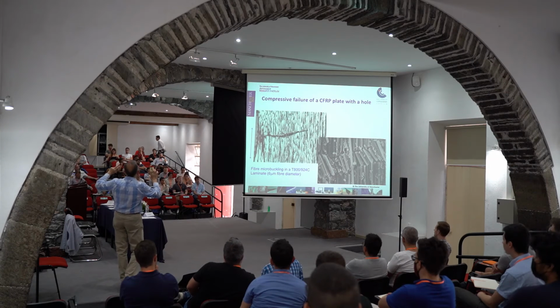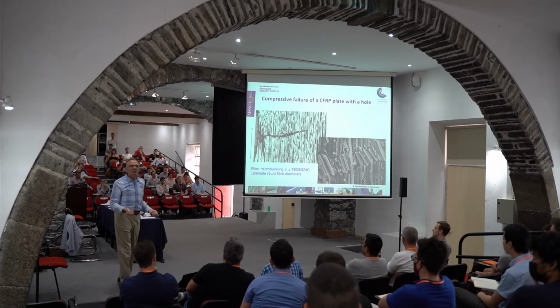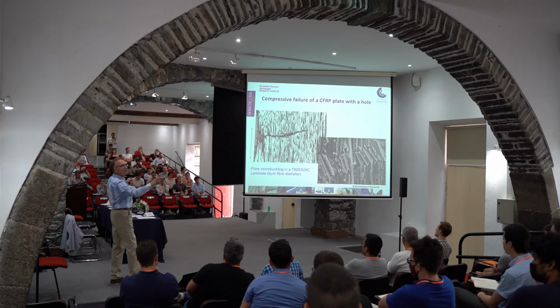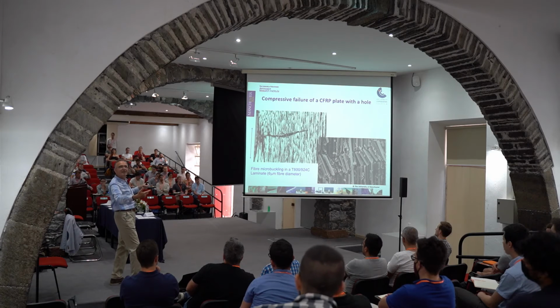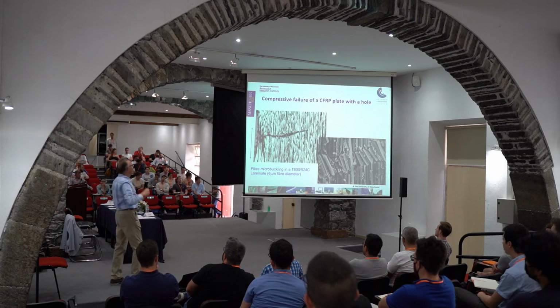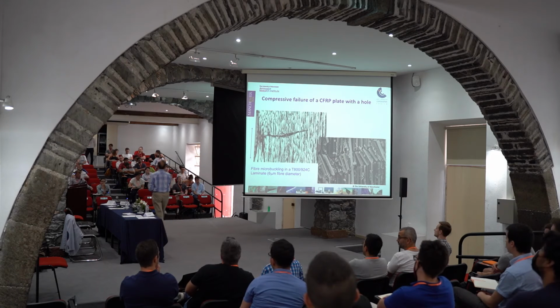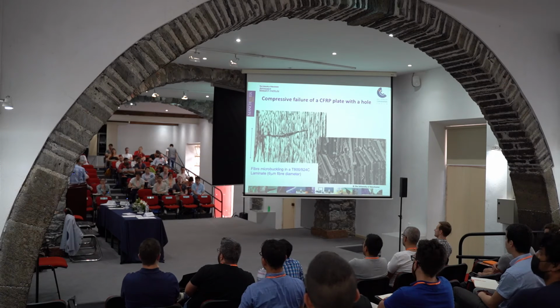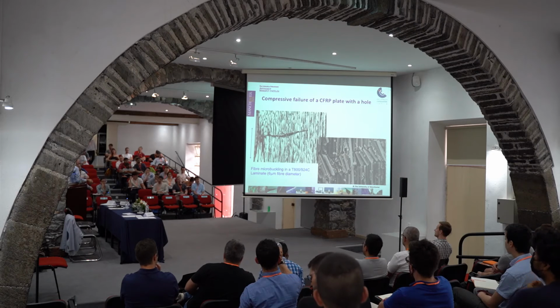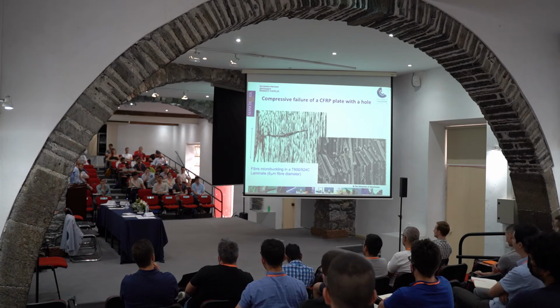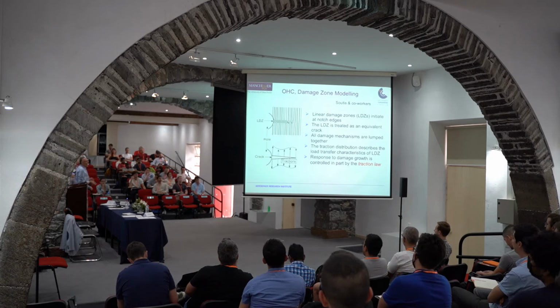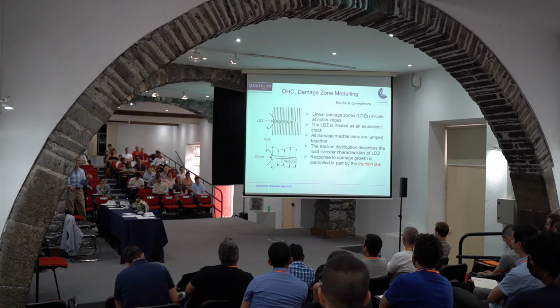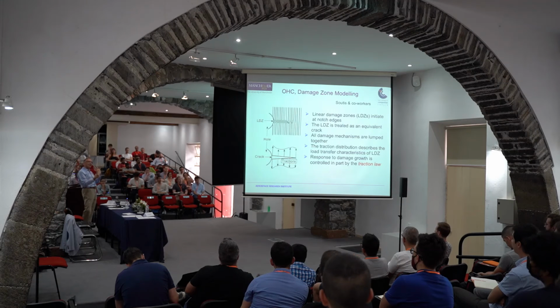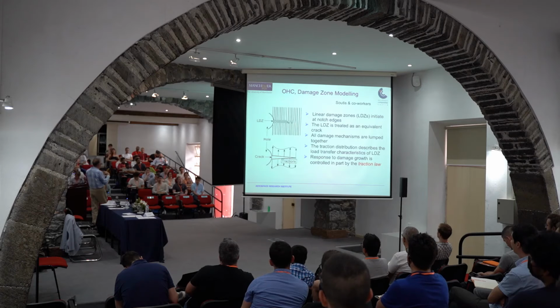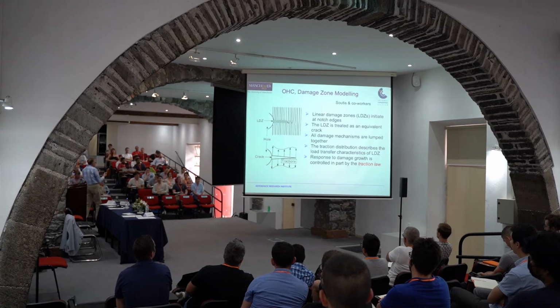And if you look at that low magnification optical microscopy, you're going to see something like a specimen loaded in tension, with a transverse crack at the edge of the hole propagating across. And when it reaches a critical length, ductile story. Have you done ductile? No? Not in metals? So I use some of the concepts of ductile. But under compression, that crack is not just a tension crack, it's a compression crack, and it's the fiber microbuckling we've seen earlier. The fiber instability. And I used fracture mechanics concepts developed for metals. So can you see we learn from that community? But we have to adapt, we have to introduce the right changes to account for the new system we have created.